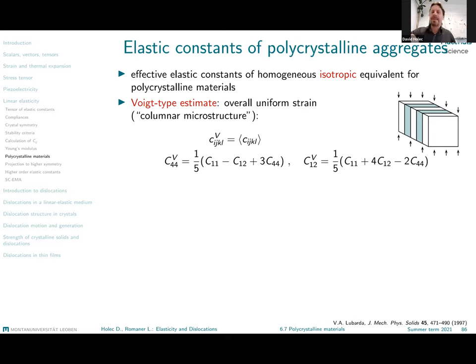One is called Voigt's type of estimation, in which we apply to all of our single crystalline grains the same deformation. All of those are subjected to the same strain. When I apply a strain to my aggregate of grains in Voigt's limit, then all of those grains, independent of their crystallographic orientation, have the same strain. Now, because they are not isotropic, the resulting stress in an individual grain depends on the actual orientation. And therefore, the macroscopic stress acting on my polycrystalline aggregate will be an average of the stresses of all of those grains.